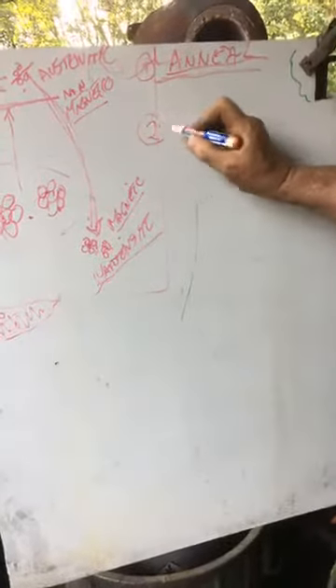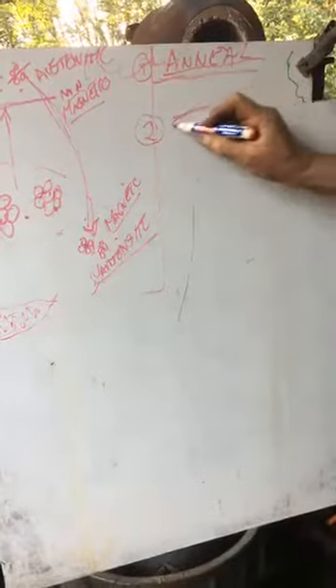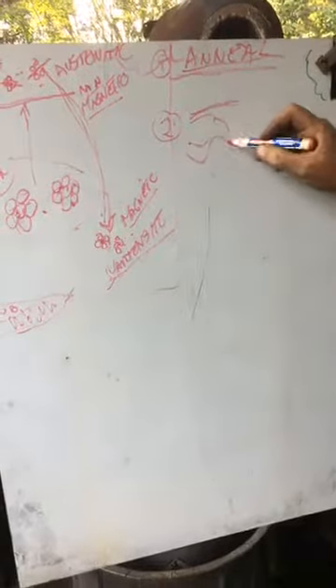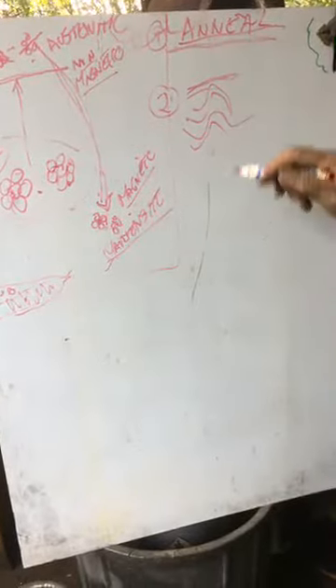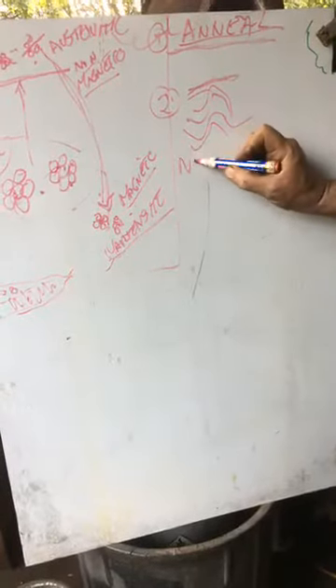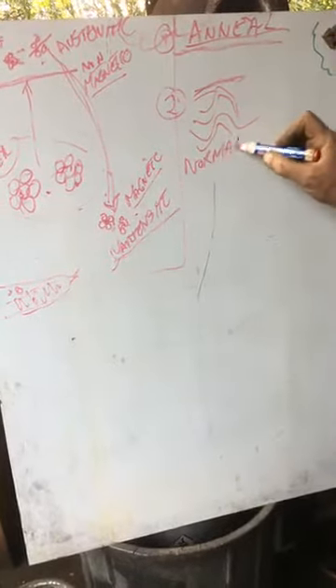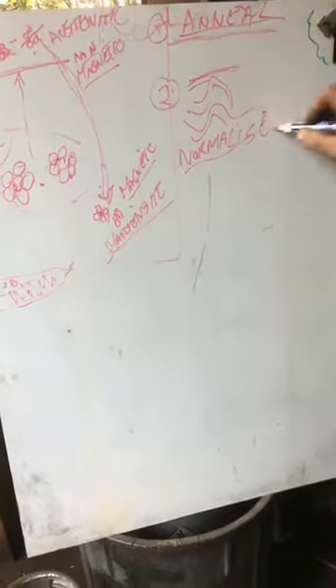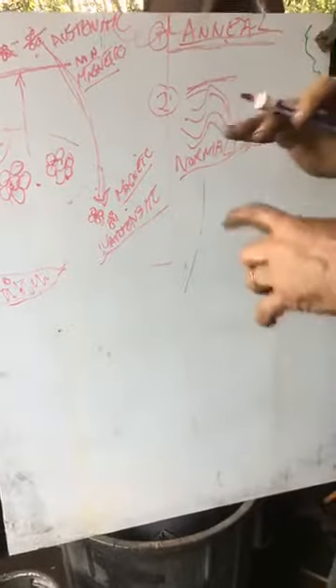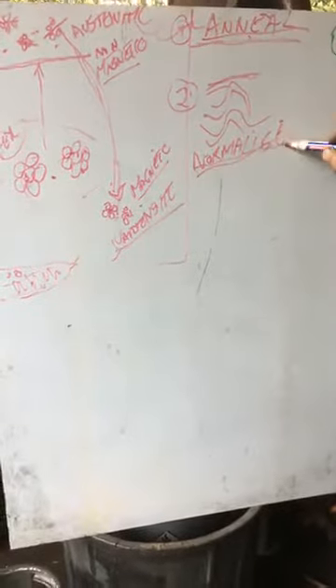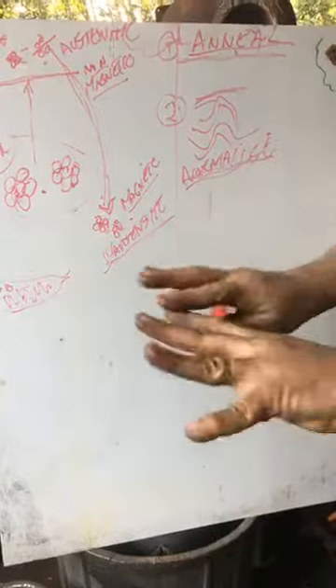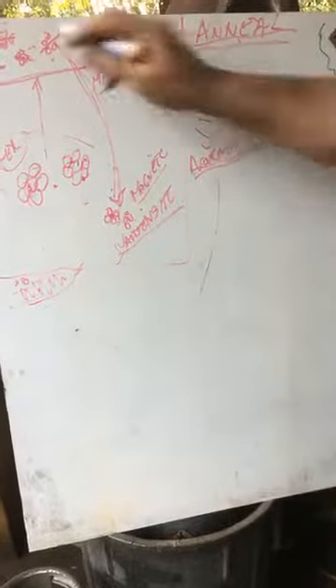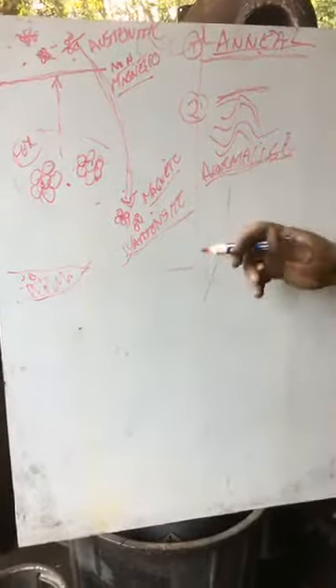So after forging, it still has a grain. You've hammered it, so that grain is kind of all hammered out. You want to normalize it. And these are all part of heat treating. So annealing, normalizing. So annealing, before you do your forging, you want to make it as soft as possible and de-stress the steel. Number two is to normalize it. So that's after forging. You put the grain all out of kilter. So you want to de-stress the steel before you harden it. Otherwise you are going to get cracks on the edge.